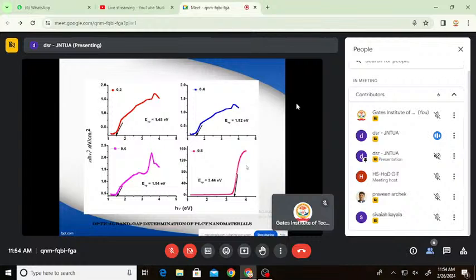But interestingly, the increase in optical band gap of 3.44 was achieved for Z equal to 0.8 composition, which may be due to increased lanthanum content. The obtained wide bandgap value for Z equal to 0.8 composition may be argued due to the cation exchange.